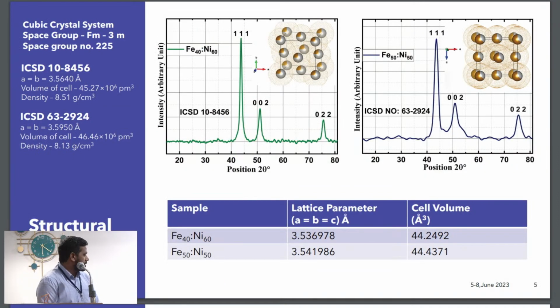This is my XRD structural properties of the iron nickel alloys. I have prepared 2 alloys, that is 40-60 ratio and 50-50 ratio. I confirmed the crystalline nature of both the materials by ICSD data 10 8456 and 632924. Both confirm the cubic crystal structure, and these are the standard values. I calculated the lattice parameter and the cell volume of the material, and it is seen that our material decreases the cell volume.